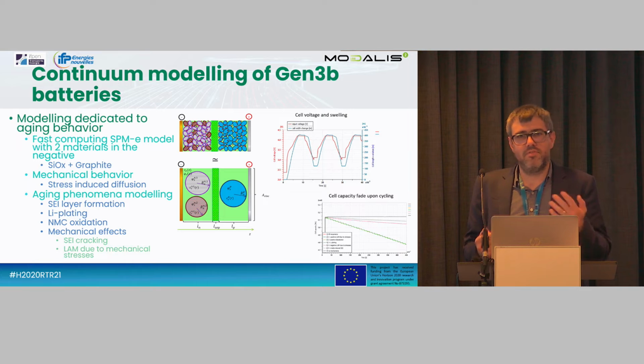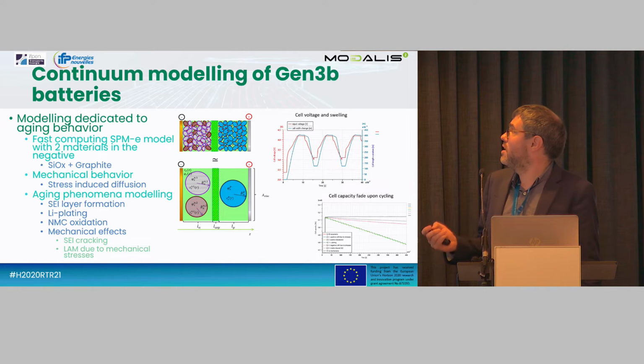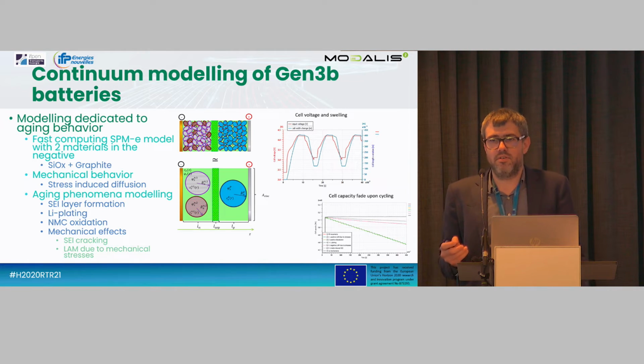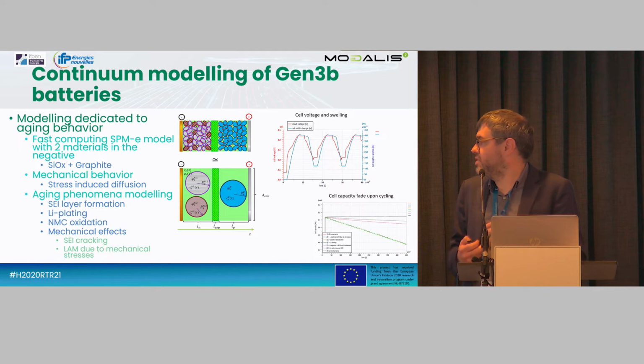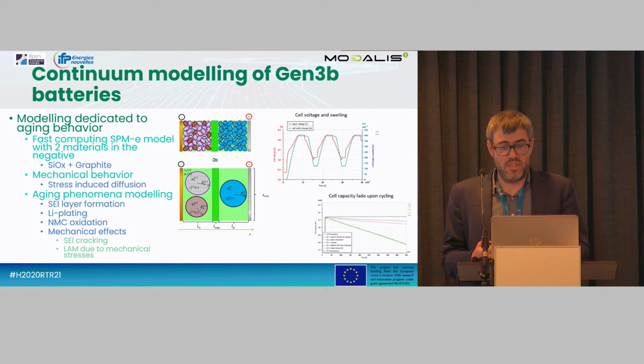And this is really interesting for integrators in order to account for this swelling at the whole system level and take into account the fact that the battery for one cell will grow by 0.5 millimeter. So if you have 100 cells, you have a higher swelling that needs to be taken into account at the system level. Then the mechanical behavior is also taken into account for the electrochemical behavior of the cell and also for the aging. So a lot of aging behaviors are impacted by mechanical aspects. So we added into our model many aging phenomena, especially the mechanical effects such as particle cracking, loss of active material, and SEI cracking.